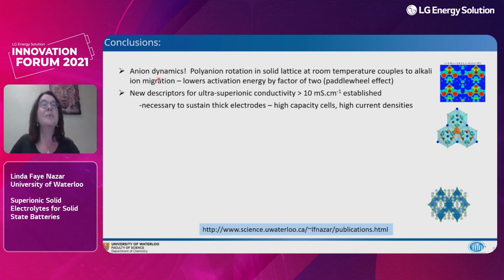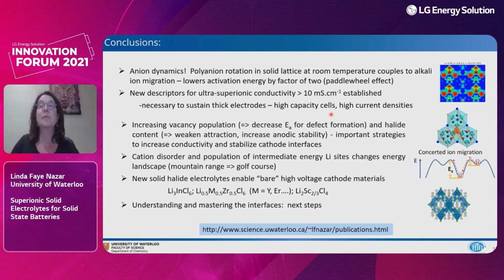So I hope I've convinced you of the importance of anion dynamics in lowering the activation energy. I didn't really get into the numbers, but it's on the order of a factor of as much as 2 by this paddle wheel effect. I've also shown you some new descriptors for ultra-superionic conductivity that are necessary to sustain thick electrodes. This is with the stepping stones and concerted ion migration. And these are really critical strategies, I think, going forward to develop new solid-state electrolytes.